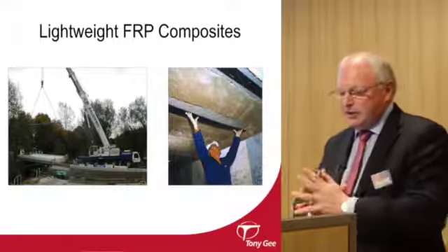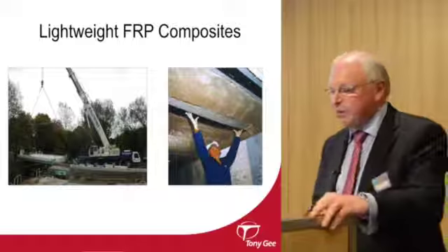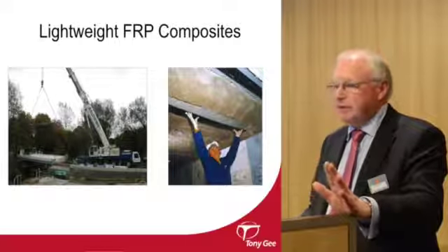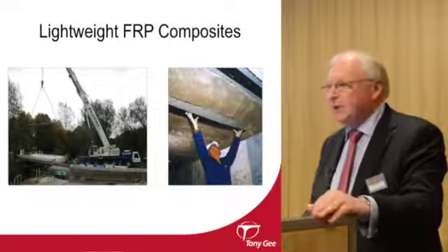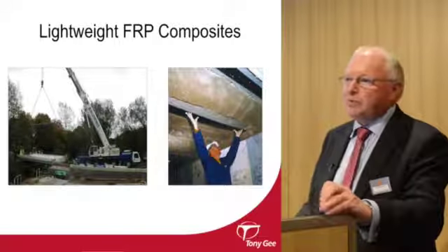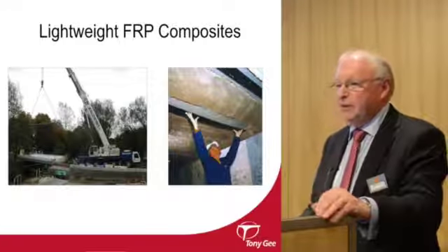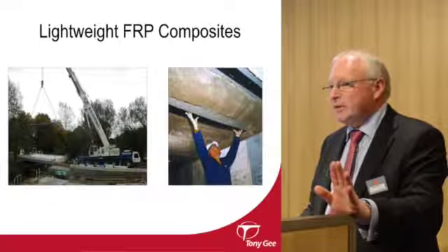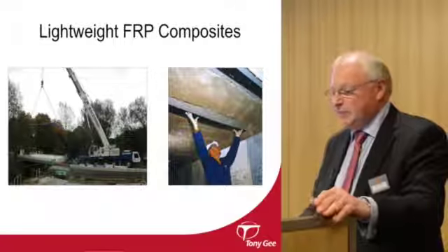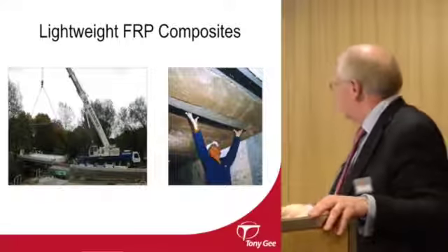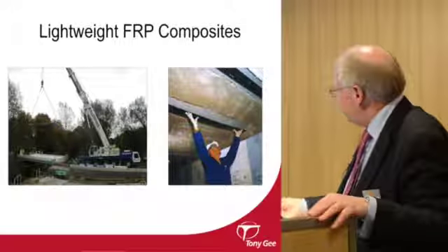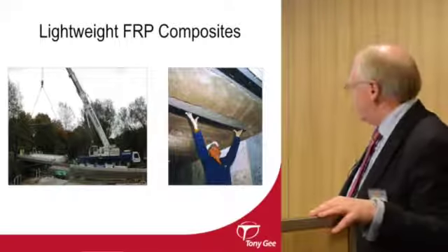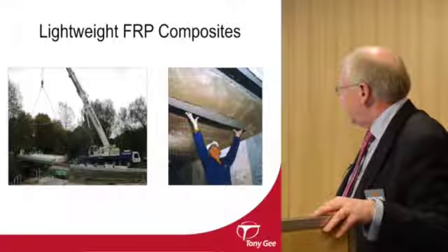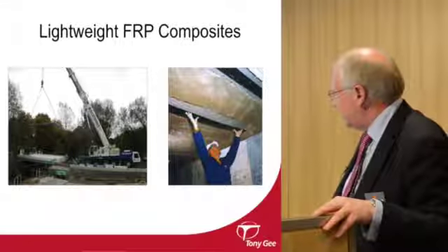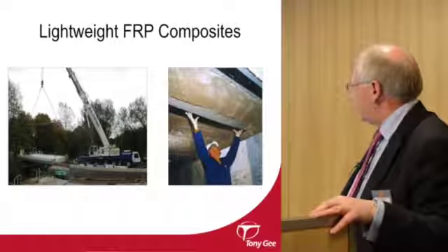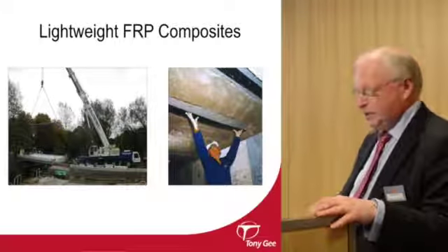So I guess in addition to having high strength and stiffness, one of the main advantages and characteristics of composite materials is the fact that they are so light. Typically in density terms, you're looking at 1/5 to 1/4 that of steel. And we need a lot less cross-sectional area to give the same strength as well. So needless to say, the guy on the right here was just applying one plate, and you probably got a mate over this end, but that was it. 2 guys can quite happily apply quite a long plate. And you can see here craneage for a whole FRP, a glass fibre reinforced bridge, can be considerably reduced as well. So there are obvious savings associated with lightweighting.